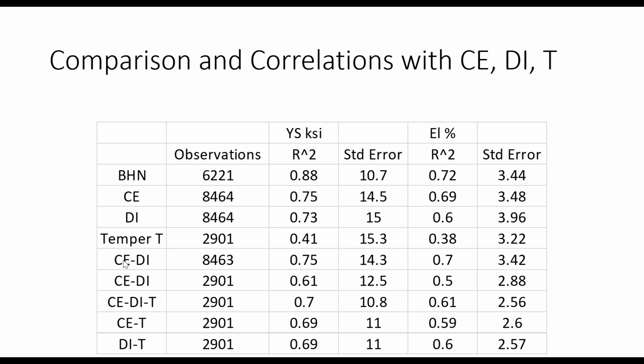And so if I look at carbon equivalent up here plus DI for this whole data set, you can see that I get a marginal improvement, but not much. If I do it with a limited data set, and the reason I use a limited data set is because I only have 2,900 points with the tempering temperatures included, my correlation goes down compared to this, but my standard error goes down much more dramatically. So if I want to predict, carbon equivalent plus DI plus tempering gives me probably the best correlation, and one of the nicest is DI versus tempering temperature.